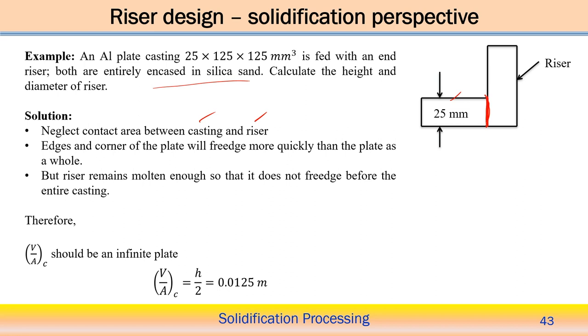First, we need to calculate the volume by area ratio for an infinite plate, because we have the dimension 25 by 125 by 125 millimeter, and compared to the other two dimensions the thickness of 25 is small. So we can assume an infinite plate such that volume equals A, B, C and surface area equals 2 into AB plus BC plus CA. So the volume by area ratio equals ABC by 2 into AB plus BC plus CA.